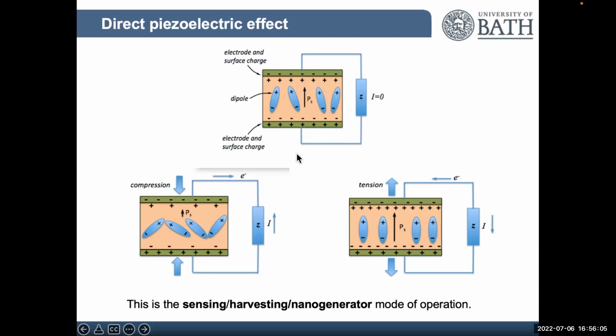And that's because you want to get sort of charge neutrality. There'll be no current, there'll be no potential difference across that device or across that particle. So it's only when you apply a compressive load that you change the polarization of the material. So some of that surface charge, that screening charge, is now free to take part in current flow.